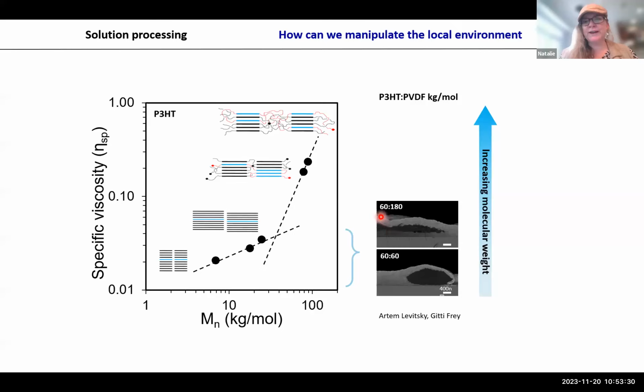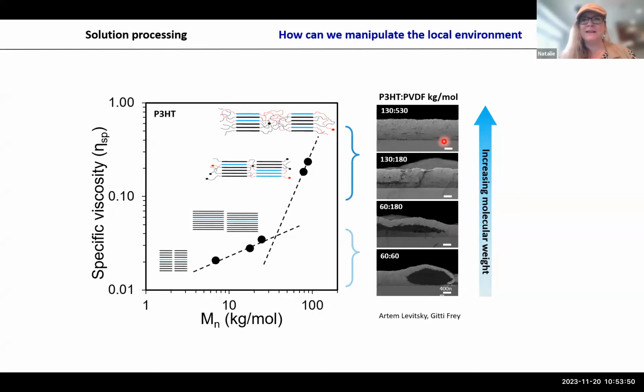If you change the molecular weight to 60 kilogram per mole for P3HT and relatively low molecular weight for PVDF, you see the two polymers massively phase separate. So these bright areas are P3HT rich, the dark area here is PVDF rich, this dark here is the substrate. Once we change to molecular weights where both of the materials are above Mc, you see we get pretty homogeneous films. So it's this region over here.